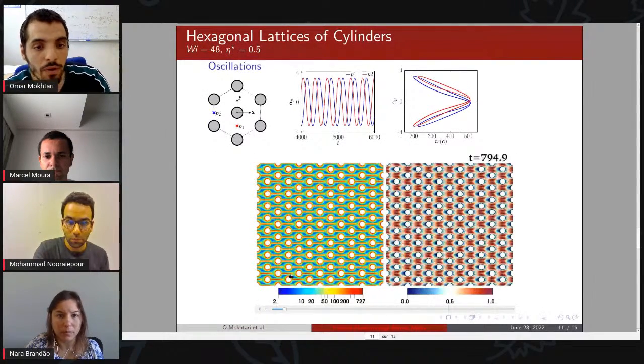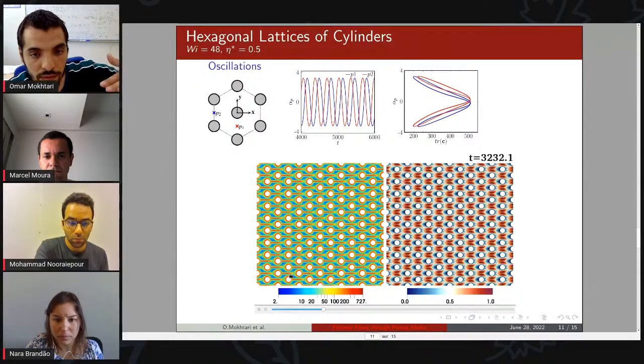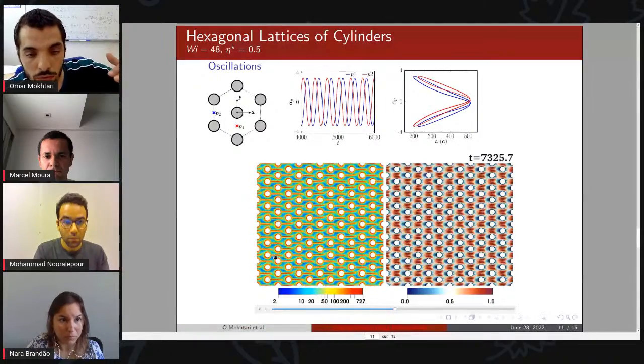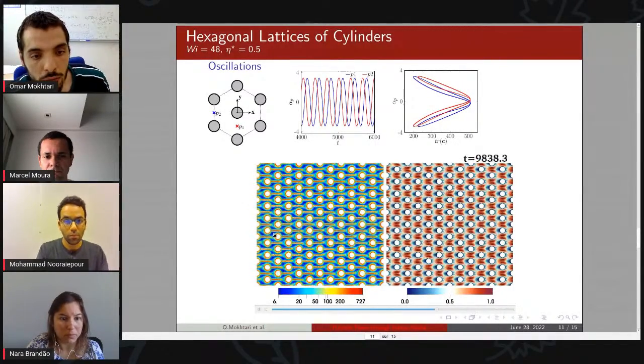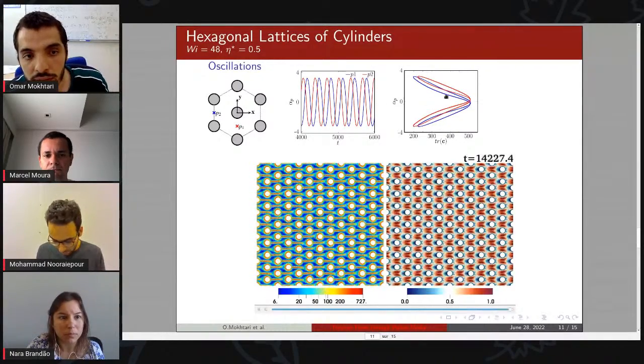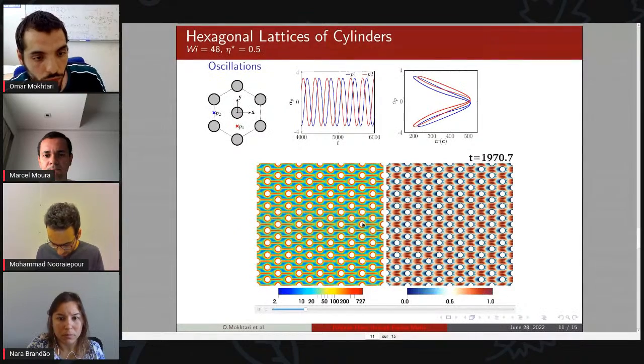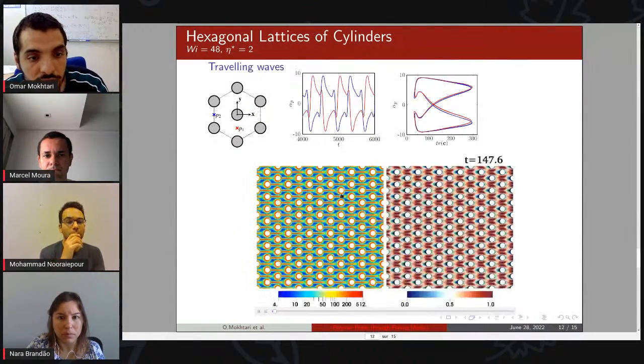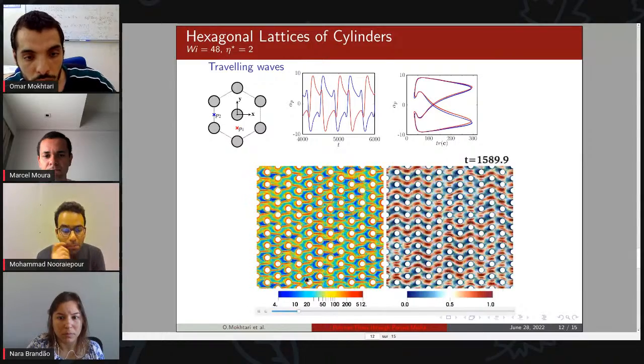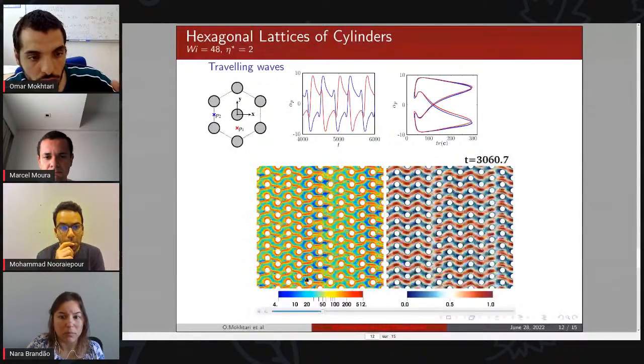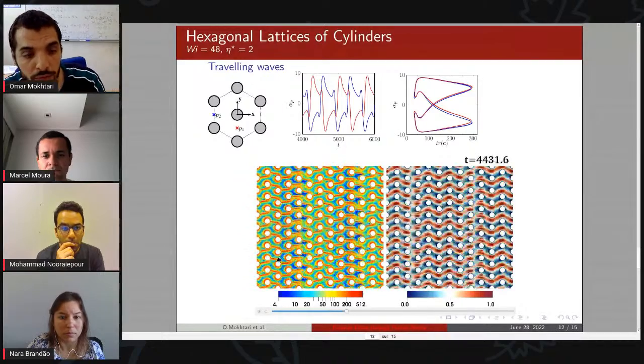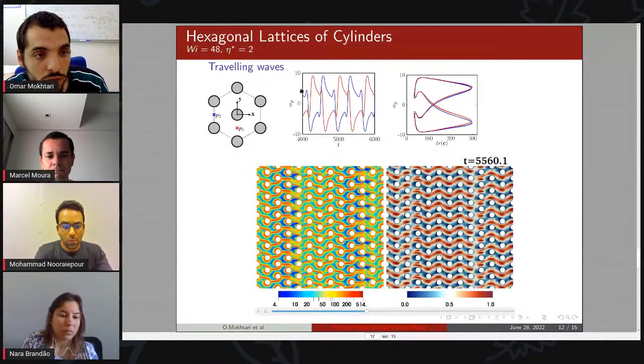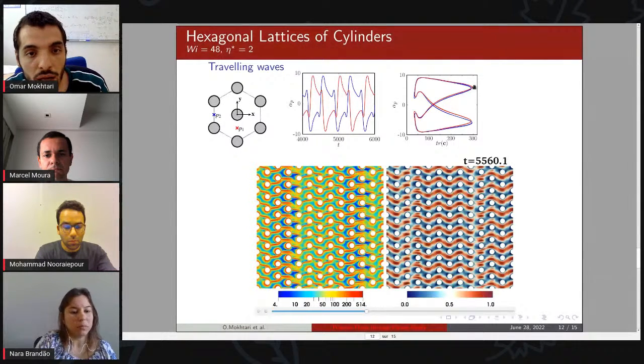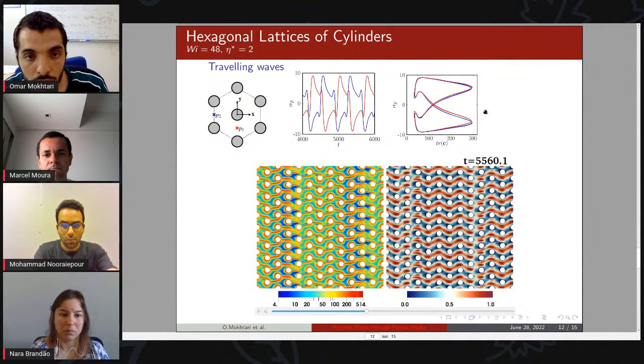By further increasing the Weissenberg number, we can see, due to these coexisting stable states, the beginning of fluctuation. We have a periodic oscillation of the strands around theta equals 0. And by further increasing the Weissenberg number, we can see that the oscillations are no longer periodic, and we have a propagation of traveling waves. So the fluctuations are no longer periodic and are around two angles.